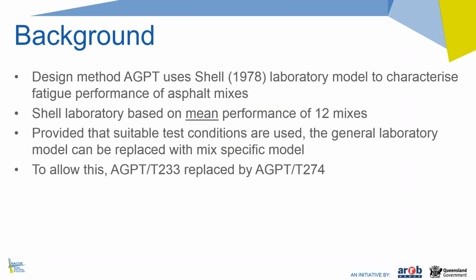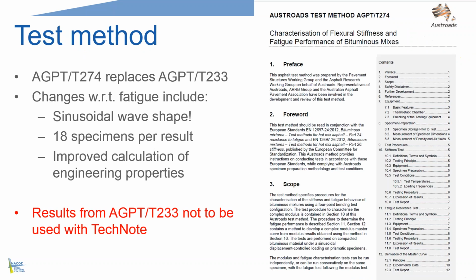Okay, so again, taking a step back, the reasoning why we argue that we can do this within our current design framework is that the design method in the Austroads Guide to Pavement Technology uses the Shell 1978 laboratory model to characterize the fatigue performance of asphalt mixes. That laboratory model is based on the mean performance of 12 mixes. And provided that we use suitable test conditions that are similar to what Shell used, the general model can be replaced with a mix-specific model. And to allow that, we did need to make changes to the test method, and that is one of the reasons why T233 was replaced with T274.